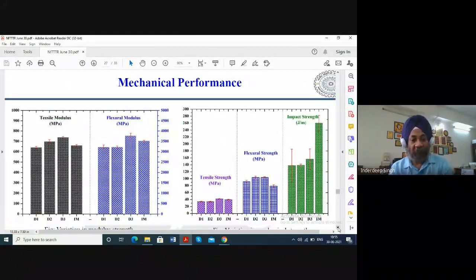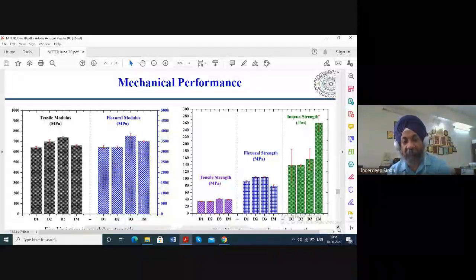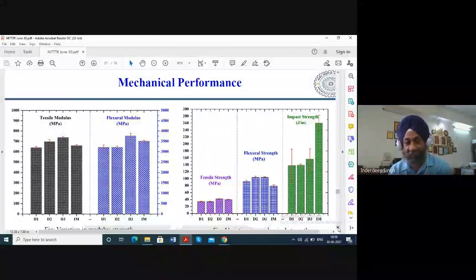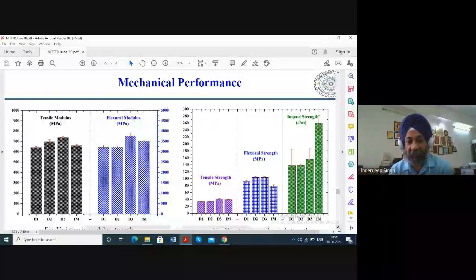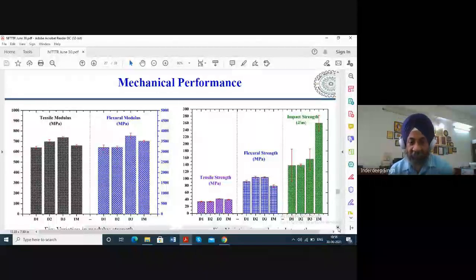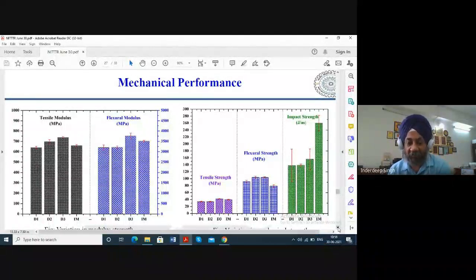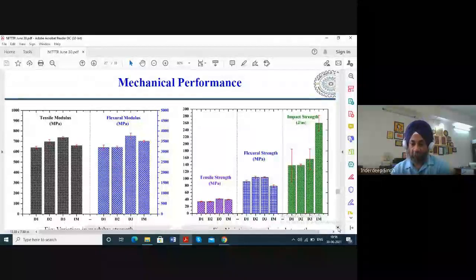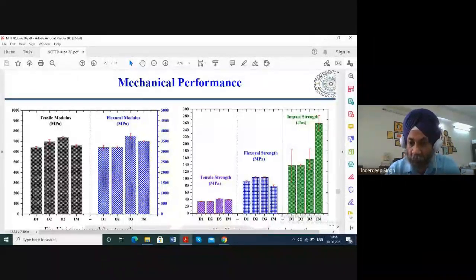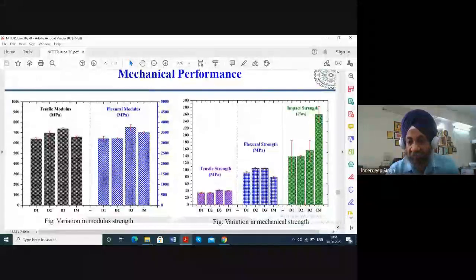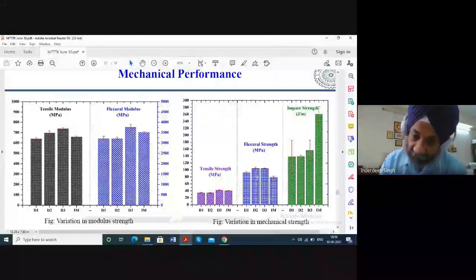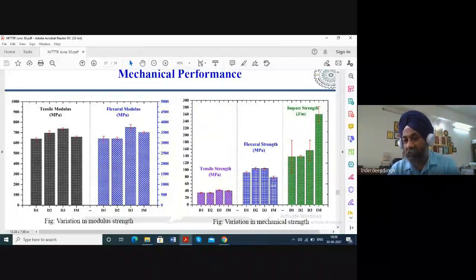And if you see the D1, D2, D3, if you compare the fill density, all of us know, no need to discuss that, the higher the fill density, the better will be the performance. So here we see that with the fill density, D3 is giving us the maximum tensile modulus and maximum flexural modulus, and it is comparable, even slightly higher than the injection molded parts. Similarly, the strength values also, tensile strength is comparable. Even the flexural strength of the FDM parts is better as compared to injection molding.